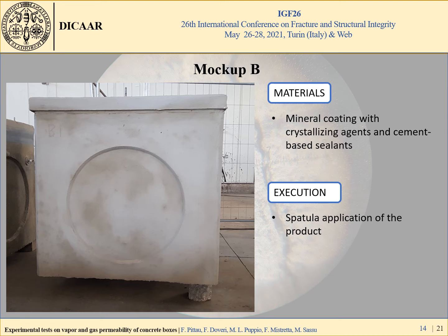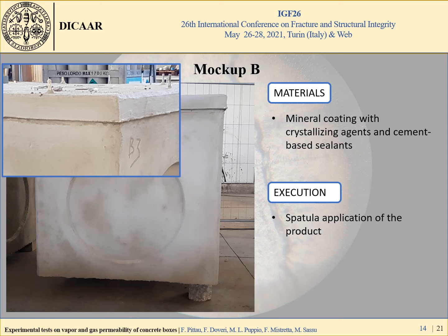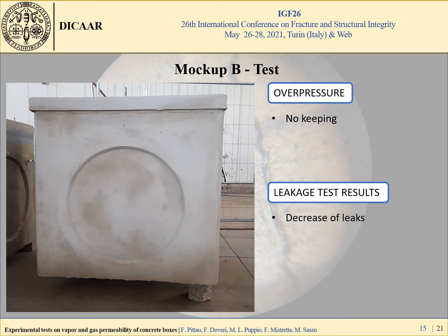Here we used only one material, the mineral coating, and the processing on this mock-up was considerably easier. The coating was applied in 2 layers, both on the surface and discontinuities, and an unskilled worker was needed to apply the material. During the test, the behavior was not good. No overpressure was maintained, and the leaks decreased, but not as much as we expected.